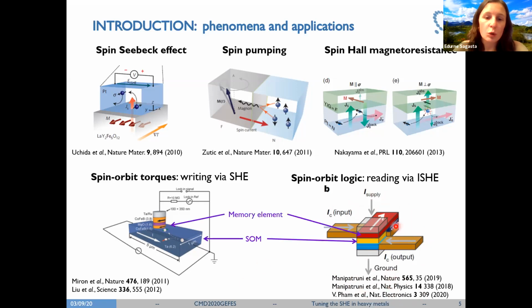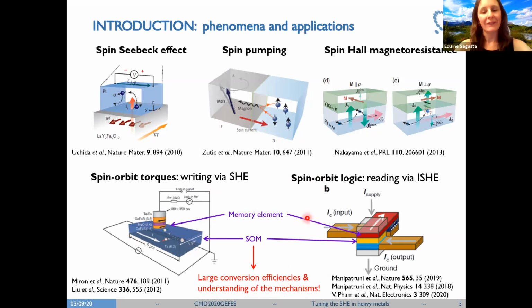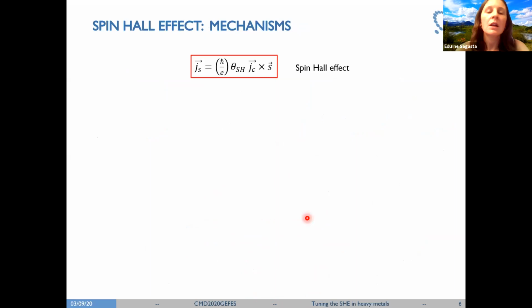So basically what we see in these two experiments or proposals is that the spin orbit metal, where the spin to charge current conversion is occurring, is useful for writing and reading the memory element. But of course, for this, we need large spin to charge conversion efficiencies. And for this, we need to understand properly which mechanisms are dominating the spin Hall and the inverse spin Hall effect. So, I said that the charge current and the spin current in the spin Hall effect are related by the spin Hall angle.